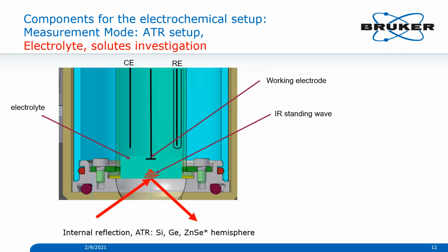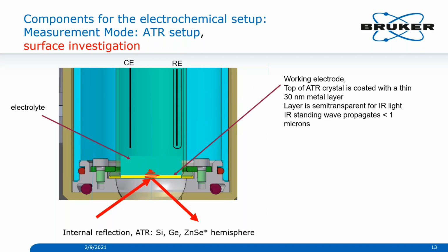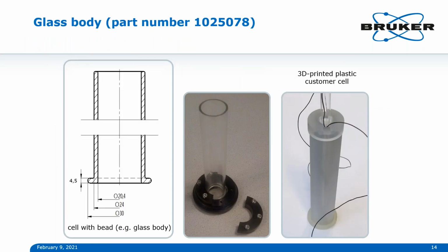But we can also do another experiment. If we cover the top of our ATR crystal with a thin layer of metal, thin meaning typically about 30 nanometers, it is semi-transparent for infrared light. As you see here, an evanescent wave will also be created in this setup. But we use this layer as a working electrode. As a result, we mostly see what's going on at the surface of the electrode during these electrochemical experiments. So as you see, there are 3 basic experiments you can do: 2 experiments with ATR and 1 experiment in reflection. So the next important question is how you can introduce your electrochemical cell for such measurements.